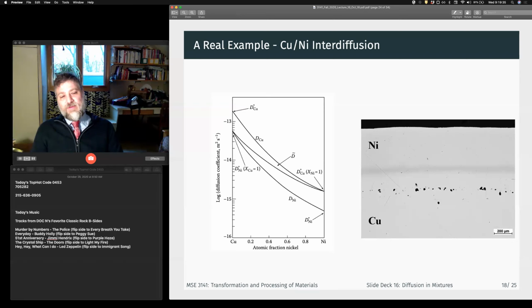right? So if the copper is always moving faster towards the nickel than the nickel is moving back, I'm going to have higher vacancy formation. So the size is not really the only thing that matters, right? It's also the bonding. Well, they're metals, so we still have metallic bonding, so we don't have ionic charge in the same way, right? But it's the bonding. Nickel is much stiffer than copper. It has a higher melting temperature, right? So nickel forms essentially stronger atomic bonds than copper, right?